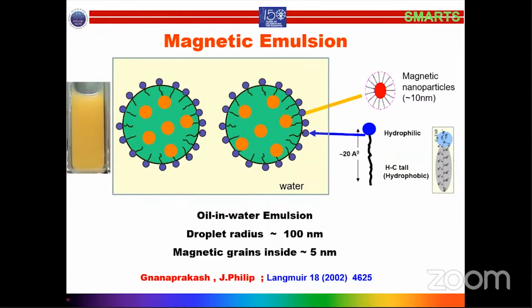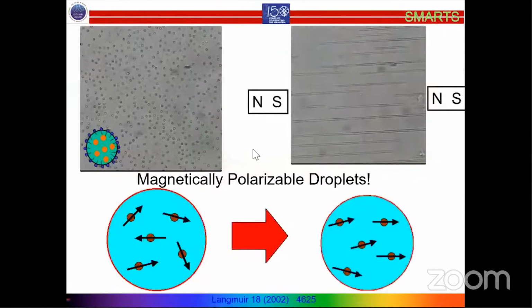As you all know, these colloids and emulsions are thermodynamically unstable systems, but you can make them kinetically stable by using some kind of stabilizers and surface active species. And as you've seen in the video, initially they are random and there is no net magnetization. The dipoles which are randomly oriented within the droplets are superparamagnetic. When you apply a magnetic field, you can control the magnetic interactions. As you have seen, the magnetic interaction you can tune. That means you can control the interparticle spacing.